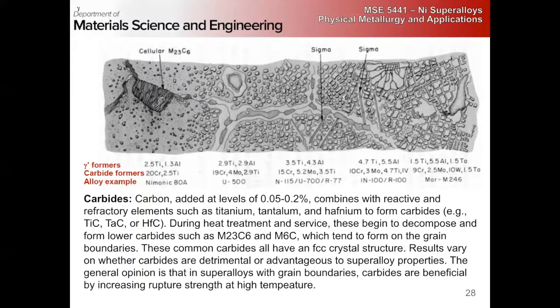But we do know that it does segregate to grain boundaries and is important for additional creep strength because it lowers the grain boundary energy. Carbides are also very important for high temperature creep strength. Right, so there's added carbon at very small percent where they'll combine with the refractory elements and form these blocky carbides on the grain boundaries, right, that during service and heat treatment, they'll form lower carbides such as the M23C6 and M6C, which form on the grain boundaries, right? And these are all based on the FCC crystal structure,